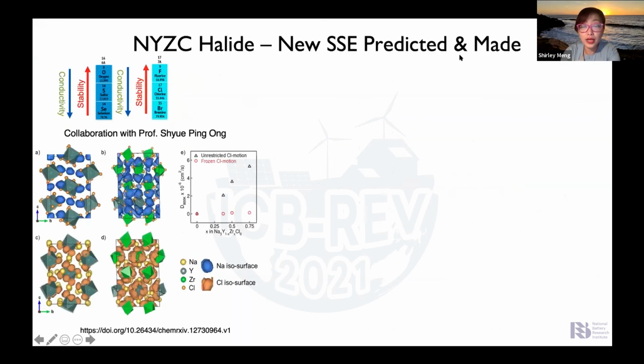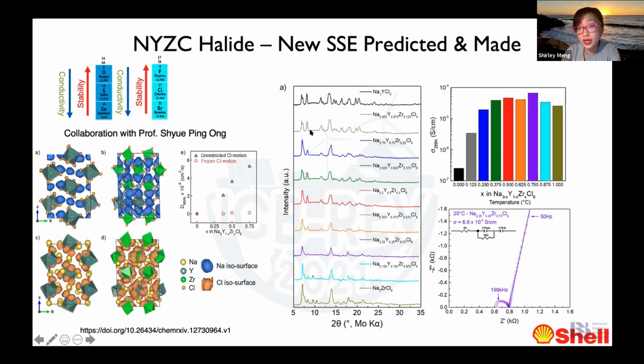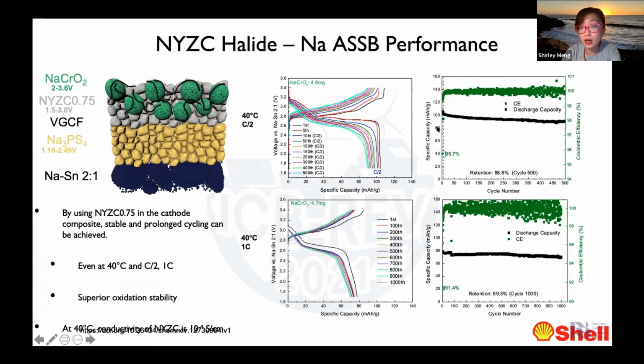Regarding the new electrolytes, I think lithium is not the only carrier that we can utilize. You can actually use sodium. We can find the sodium equivalent of these halides and get very nice ionic conductivity at room temperature. So what we show here is you can make these solid electrolytes with very good room temperature conductivity, and the cell cycles pretty well. We demonstrated 1,000 cycles in small-scale, laboratory-scale test cells. And this work is indeed funded by the energy company Shell Corporation.